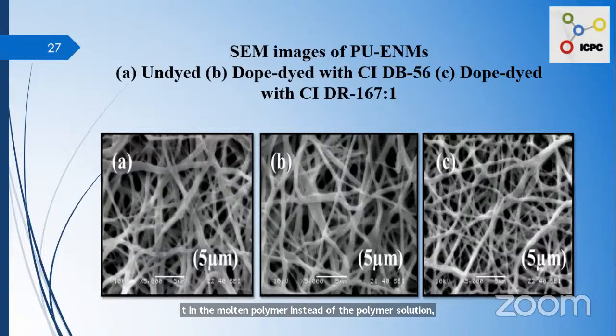So these are the images which show the smooth morphology of the nanofibers with no beads, indicating that the polymer concentration of polyurethane, the selected solvent system and employed electrospinning parameters were successful. Whereas figures B and C show the morphology of the dope dyed polyurethane electrospun nanofibrous mats, and the undyed nanofibrous mats was similar. So this shows that the dope dyed and pure nanofibers were unaffected by curing temperature and the dyes were properly diffused into the fiber using the polymer system.